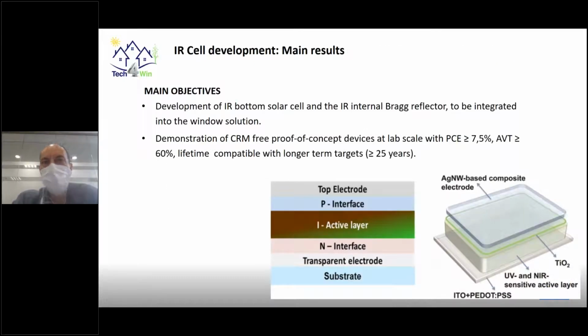I will present the main results that we have achieved in terms of the development of the infrared and ultraviolet cells. Relating to the infrared cell development, the main objective at cell level is the development of the infrared bottom solar cell with the infrared internal Bragg reflector that has to be integrated afterwards into the window solution. Quantitatively, we want to demonstrate a critical raw materials free proof of concept device at lab scale with an efficiency higher than 7.5% and with a visible transparency higher than 60%. And also, what's very challenging, we need to work with processes and architectures compatible with the long-term lifetime targets defined of 25 years.